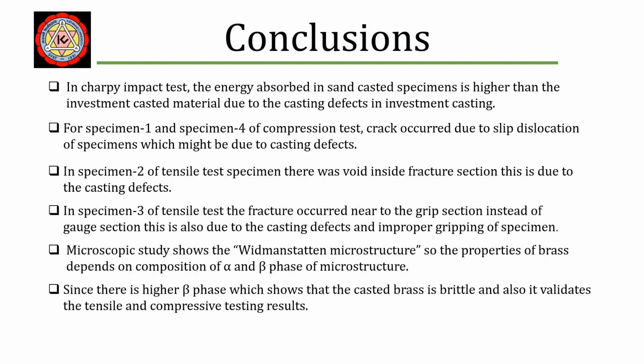So, from all the tests, the following conclusions can be drawn. In the Charpy impact test, the energy absorbed by the sand casted specimen is higher than the investment casted material due to the casting defect in investment casting. For specimen 1 and specimen 4 of the compression test, cracks occurred due to slip dislocations of the specimen, which might be due to the casting defect.